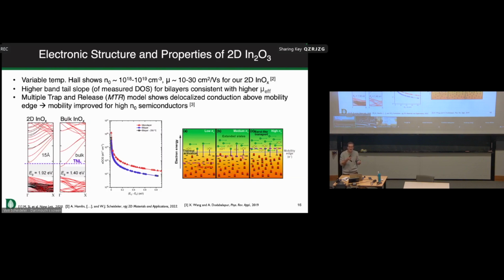Disordered materials that are polycrystalline, that are amorphous, have a little bit more complex picture. So what in fact happens is that as we add electrons to our material, we're filling up a bunch of traps. And so a good material that looks more single crystalline would be a material that has essentially a lower deep state density in the middle of the gap and a steeper tail state density right near the band edge. And there's a theory known as the multiple trap and release theory that describes this physics.